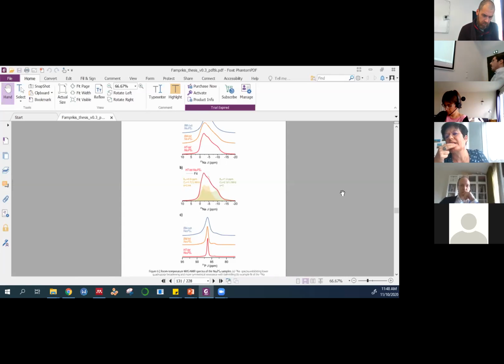Yes, well, I don't know about always. The only NMR results I have are these three that you see here. But these three can indeed be fit with the same quadrupole parameters, changing basically the broadness of the peak. And I should also mention that both the measurements and the fitting were done by Stefan Emge in Cambridge, and not necessarily by me.